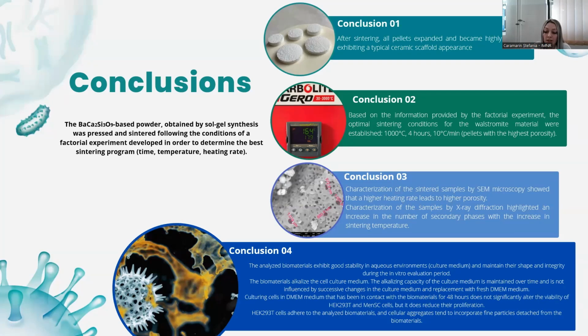The characterization of the sintered samples by SEM showed that a higher heating rate leads to a higher porosity. The characterization of the samples by X-ray diffraction highlighted an increase in the number of secondary phases with the increase in the sintering temperature. And the biological conclusions were that the analyzed biomaterials exhibit good stability in culture medium and maintain their shape and integrity during the in vitro evaluation.